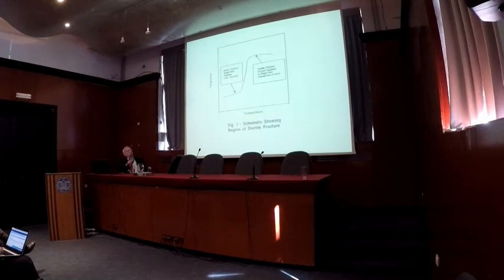This was done in terms of J, not K, but in some cases you get 20 or 30 to 1 difference in fracture toughness. And if you say, do 3 tests and average them, are you getting 3 tests down here or are you getting 3 tests up there? You don't know. So this transition region, although schematically was a nice line, is a big mess, or was a big mess.